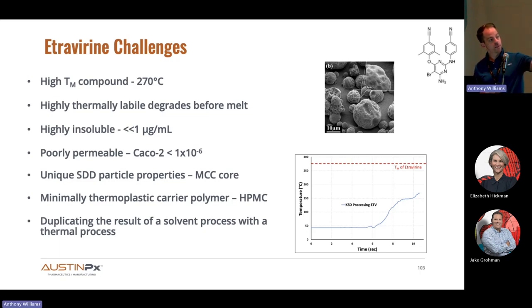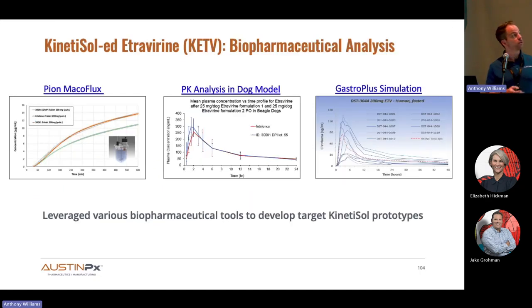Here's an example of the processing profile, pretty typical KinetiSol profile, as I mentioned before. In less than 10 seconds and at a temperature about 100 degrees below the melting temperature of etravirine, we were able to generate a single phase amorphous dispersion, matching the composition of the spray-dried dispersion. But I've laid out all the challenges from a biopharmaceutical perspective in trying to match the clinical performance of Intelence.